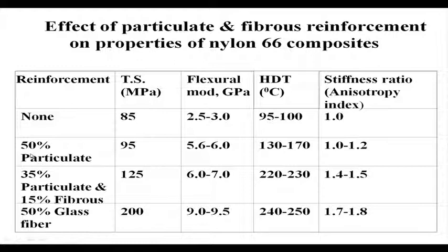Incorporating 50% particulate filler in this nylon 66 composite, the tensile strength has been increased from 85 without filler to 95 megapascal. Flexural strength has been increased from 3 to almost 6. Heat deflection temperature from 100 to 170, and stiffness ratio is also increased.